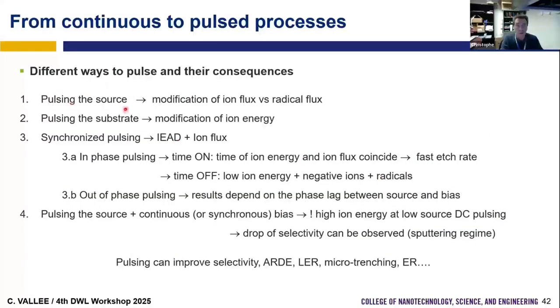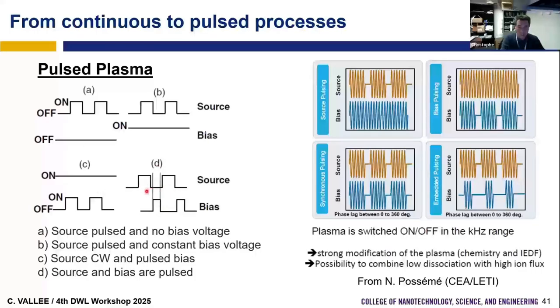So if you decide just to pulse the source, usually the source is pulsed just to modify the ion flux versus the radical flux. When we pulse the substrate, the idea is to modify the ion energy. So we can synchronize, we can be in phase or out of phase. Depending on what we do, we can try to increase the etching rate thanks to the pulsing, or we can try to have more energetic ions. For example, if you pulse in this way, now you have the off time, and you can pulse with high power or low power. If you have a low power and you bias, since you have a lower ion flux going to the substrate, you develop more DC self-bias, so the ions will be more energetic compared to the case of a continuous high power source.